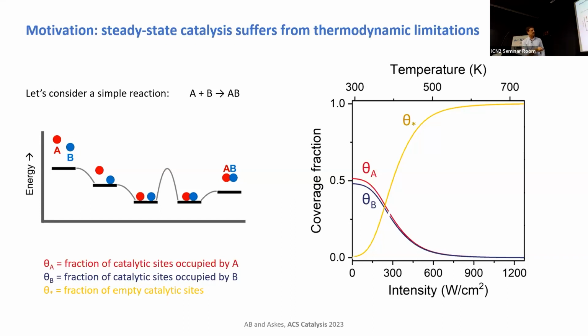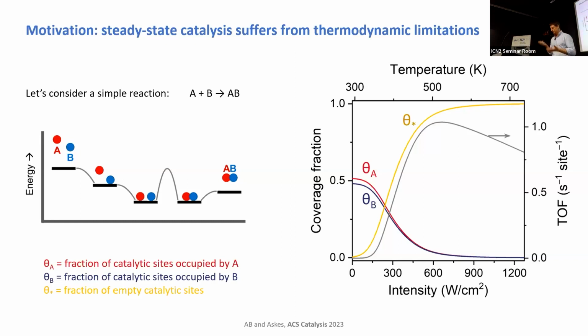And so if you plot the amount of products that you form per second, which is called the turnover frequency, then you will see that there is typically an optimum at an intermediate situation where you have a sufficient turnover frequency. And this, of course, corresponds to a state where the catalyst is essentially mostly empty. So this is the kind of compromise that you always have to play.